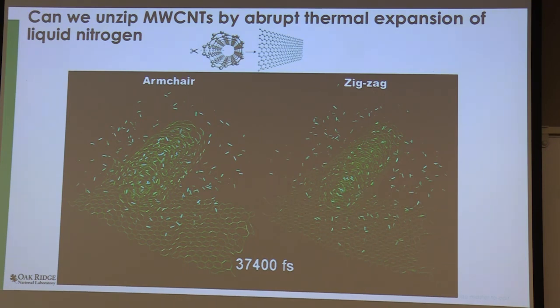potentials are not perfect. How many walls break? Huh? How many of the walls break? Here, 1. We stopped. The bigger, lower curvature one is going to break first. This down here, that's going to be rough. There's not a lot of gas that gets in a 7 nanometer diameter. You can't get much in there, so you have to have enough gas to expand to break it. I expect the second wall would break after a while.